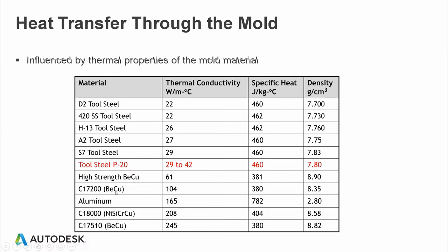I've listed different types of mold material and their thermal conductivity. Many times you may have heard from tool makers that if cooling is not efficient or they want to extract heat from critical sections, they try to use beryllium copper or high-conductivity inserts. Beryllium copper has almost eight to nine times the thermal conductivity compared to tool steel, which is also why it is a very expensive material. It's not possible to make the complete plate or cavity from beryllium copper — it's used only at specific locations where needed.